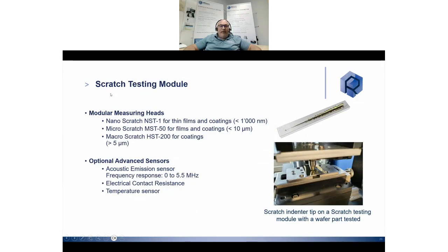We also have an important possibility, which is to scratch with our head or with our upper loading cell. We can do nano, micro, macro, and we can add sensors like acoustic emission, electric contact resistance, or temperature sensor. What is important for me when we scratch is that we mostly use progressive load, from a low load to a high load. And you see here an example on a diamond-like carbon coating. We are removing the coating due to bad adhesion in this example.